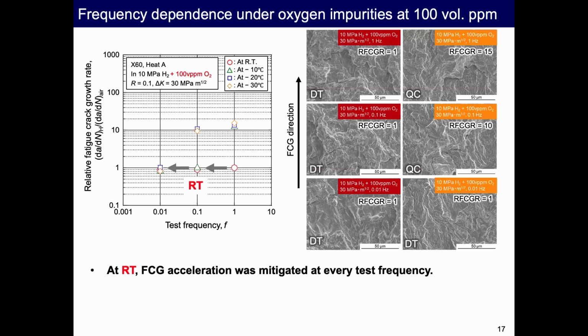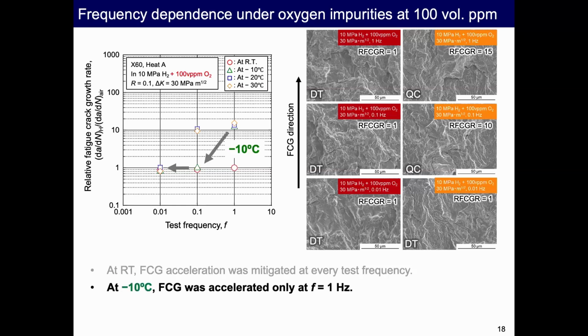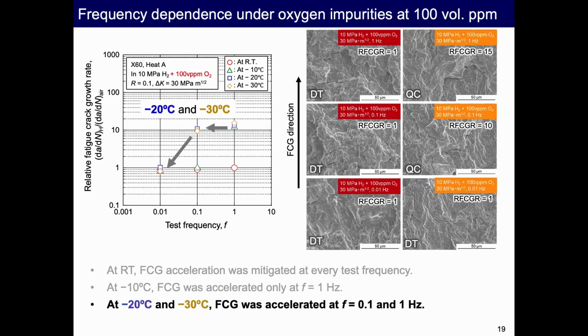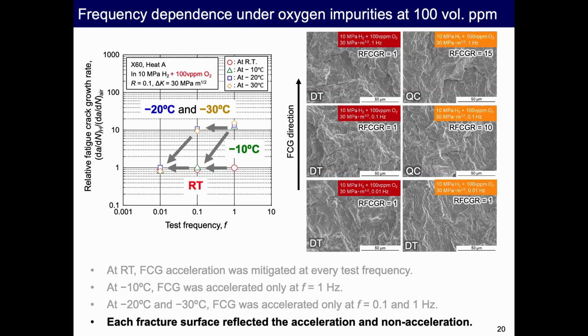That is testing in hydrogen including oxygen impurity at 100 volume ppm. This is the result. At room temperature, crack growth acceleration was mitigated at every test frequency. But at -10 degrees C, the crack growth was accelerated only at 1 Hertz. And at -20 and -30 degrees C, the crack growth was accelerated at 0.1 Hertz. Each fracture surface reflected the acceleration and non-acceleration.